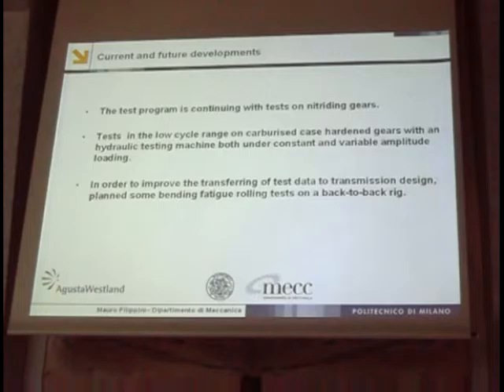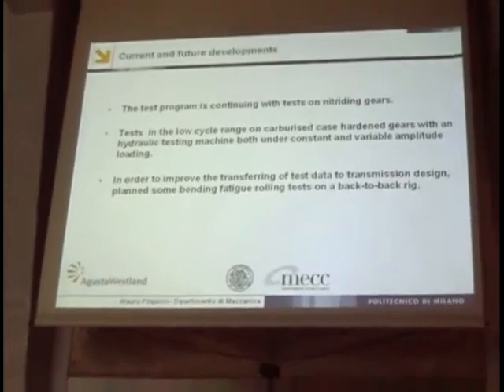In a few weeks we will start tests in the low cycle range, just to fill up the no man's land between 1,000 cycles and 10 to the power 6. We will also make tests with variable amplitude loading, because this is a service condition of interest in this industry. And we will also do back-to-back rig tests, because you need to transfer the results from single fatigue tests onto real components, where you have a statistical effect, to detect failures when testing all the teeth in one go.